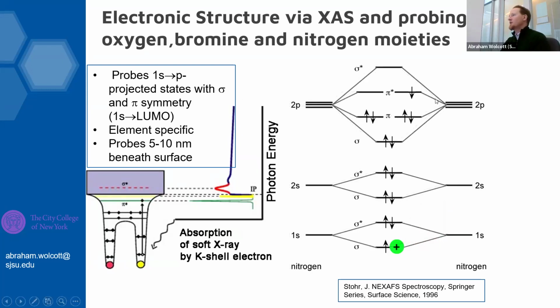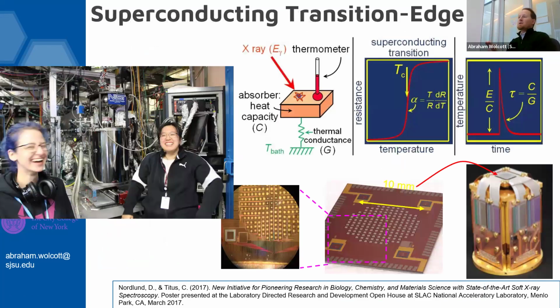Of course, you get that transition, and those available unoccupied states then host an electron, and we can get a photocurrent from our sample. Now, what's great about being at SSRL is they have hosted a number of different new tools. This is the transition edge sensor. It is basically a SQUID. It's a superconducting sensor which has background-free X-ray detection and relies on the transition edge. As an X-ray hits the detector, it slightly raises the temperature, which drastically changes the resistance, which then changes the current along this array of detectors, and therefore you can have an amazing level of specificity while getting X-rays of all energies at the same time.